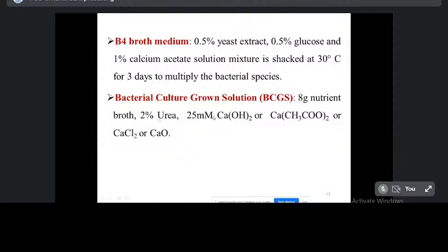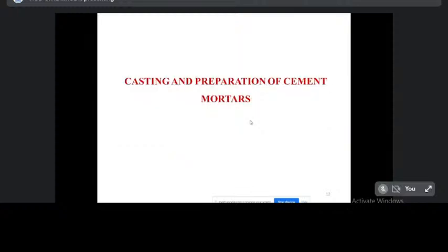Then I have changed these 4 calcium sources. The first one is 25 millimole of calcium hydroxide, then 25 millimole of calcium acetate, then calcium chloride and calcium oxide. These first two chemical components are common. The third one I have changed. Totally, I have prepared 4 combinations of bacterial culture grown solution.